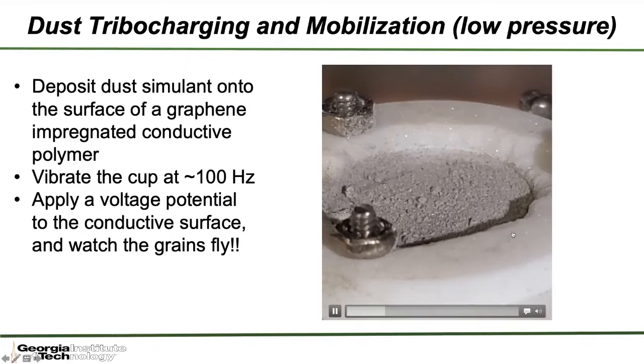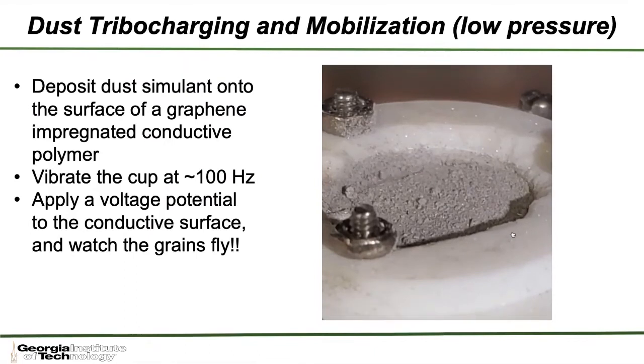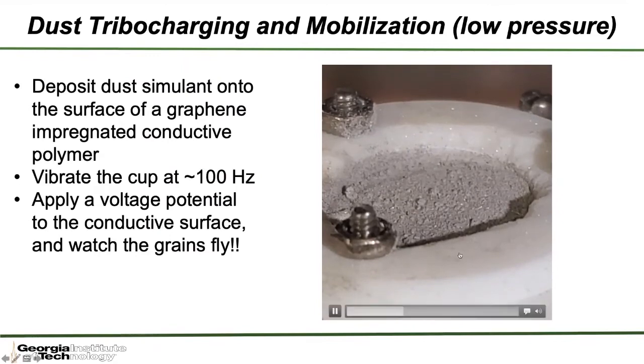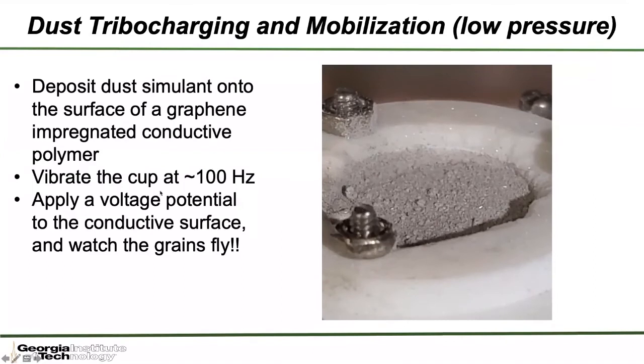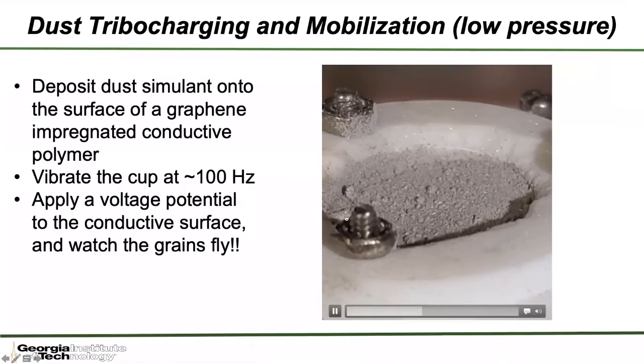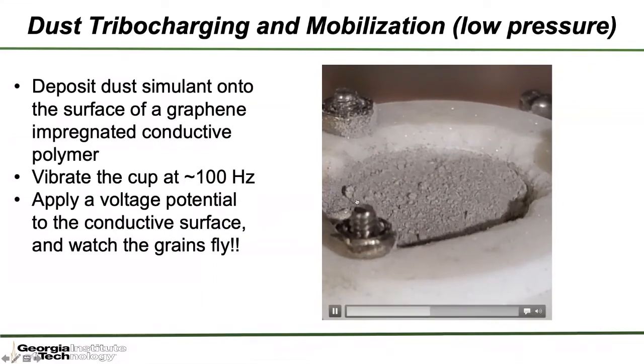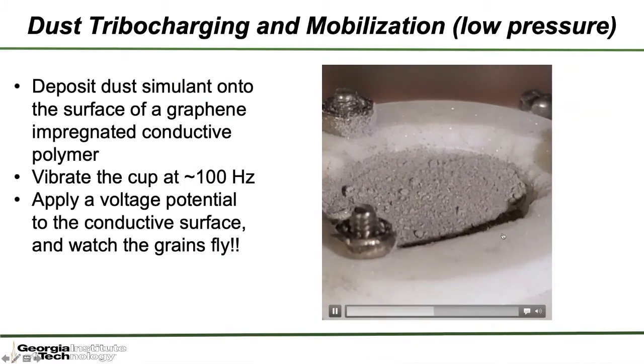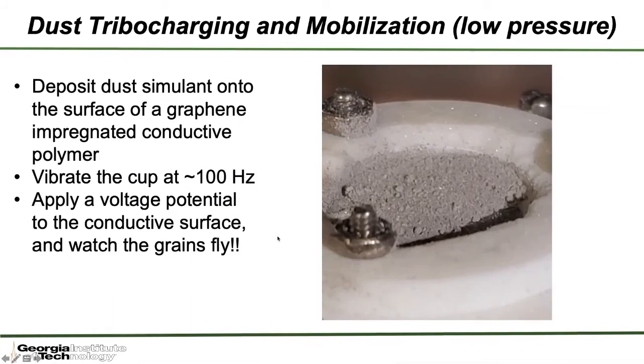So we thought, if we can get the grains to jump off of this conductive spacesuit material, then maybe we can minimize some of that grain sticking like we saw in the picture earlier, which can cause degradation of that spacesuit. And so you can see here the grains are vibrating around, and every once in a while, it's maybe a little hard to see in this video, but you can see the grains start to jump out of the cup. And so what we're doing is we're applying a potential to the surface of that conducting polymer. And since the grains are becoming electrostatically charged, the ones with the charge opposite the voltage that we're applying to the conductive surface are pushed away.